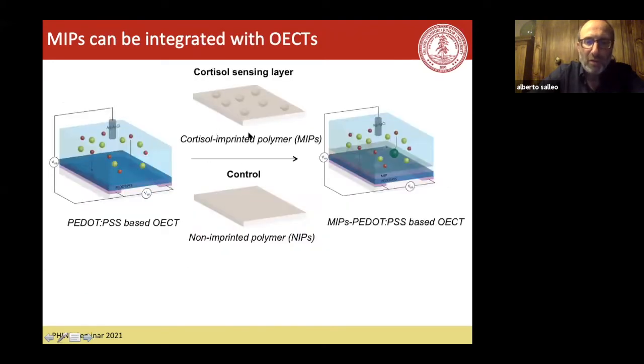And then, same principle, we put this molecularly imprinted polymer between the gate electrode that's going to push ions in the electrolyte and our device. So the idea is that our electrolyte contains the cortisol, but also contains other ions. And in principle, if the molecularly imprinted polymer binds to our cortisol, these other ions cannot make it through. And so even though we're not sensing the cortisol per se, the ions give us a sensing mechanism. On the other hand, the non-imprinted polymer should just be a barrier and not let anything through.